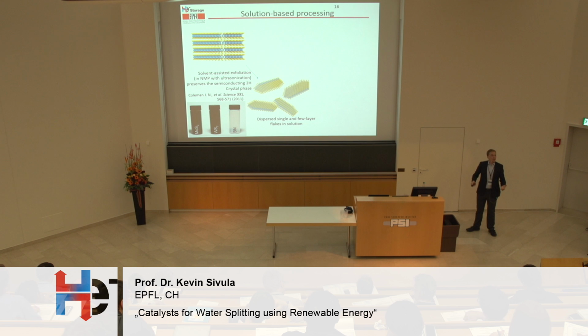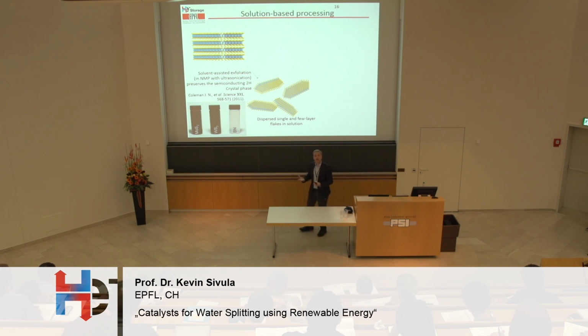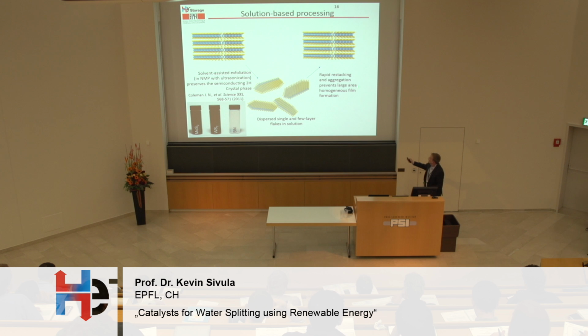Unfortunately, if we try to actually take this solution and process it into a thin film catalyst or electrode, we run into problems. As we remove the solvent, for example, by spin coating or another approach, what happens is the layers, of course, restack. And we get, unfortunately, aggregation, which prevents homogeneous film formation. So this is a definite problem for making consistent and high-performance electrodes with this material.